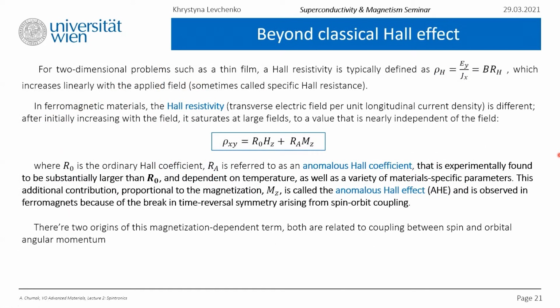So after performing Hall measurements, we will obtain a set of parameters, among which are the Hall coefficient and Hall resistivity, which are connected via this formula in the case of 2-dimensional or thin films. From that, we can determine the type of the prevailing charge carriers, holes or electrons, and their concentration. Usually, the Hall resistivity increases linearly with applied field, but it's not the case for ferromagnets.